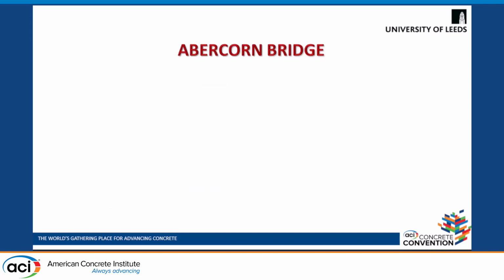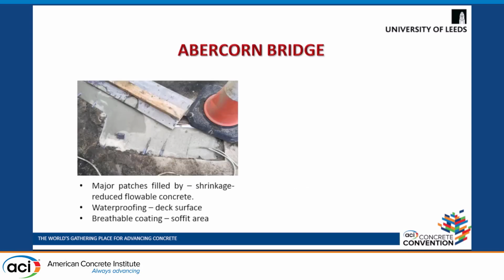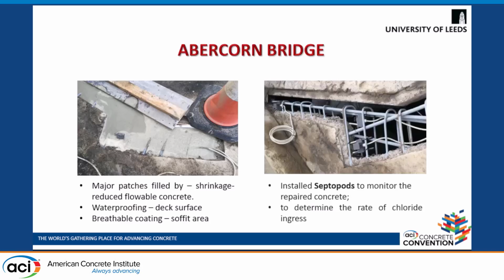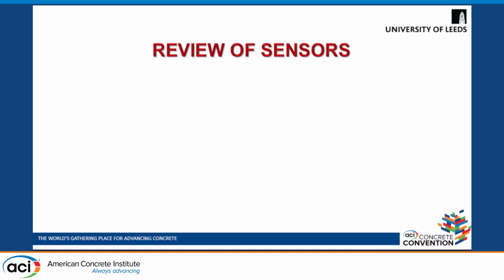Therefore, this bridge was repaired and the major patches were filled with shrinkage-reduced flowable concrete. There was a waterproofing layer over the deck surface, while on all the exposed surfaces there was a water vapor transmissible membrane, which is a breathable coating layer to allow the water moisture to evaporate. During the repairs, 3 sensors were installed to monitor the repaired concrete, to check whether this repaired concrete is working well or not, and to determine the rate of change of chloride ingress.